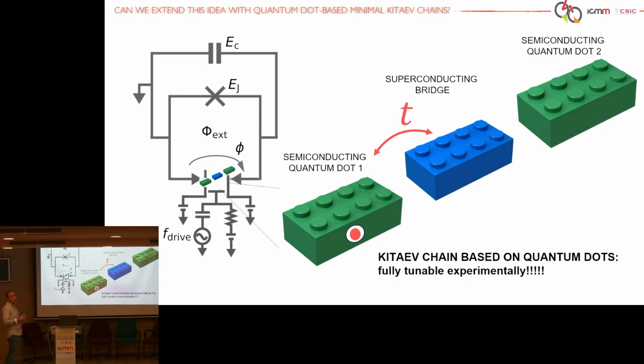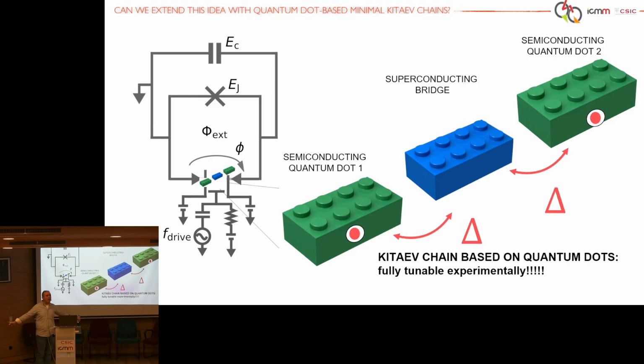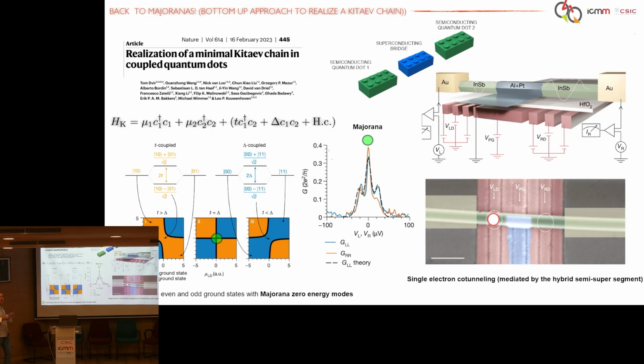And the idea now is simple, following the Kitaev model I was explaining before. You can tune the system to have single electron hoppings across this superconducting block, and for this you use Andreev levels. Andreev levels are useful for having single electrons crossing all the way across my bridge. Or, and this is very important, I can tune the system to break Cooper pairs in the superconductor and put one electron on each side of the Lego chain, okay? And this you can tune experimentally. You can tune a system in which this process delta is equally probable as the process t of single electrons, and you can have a well-defined Majorana zero mode.